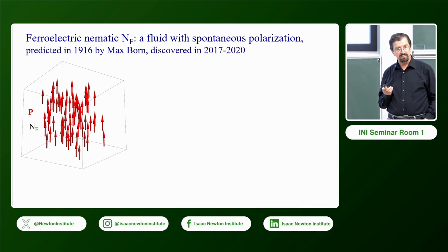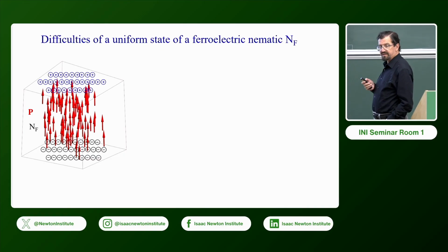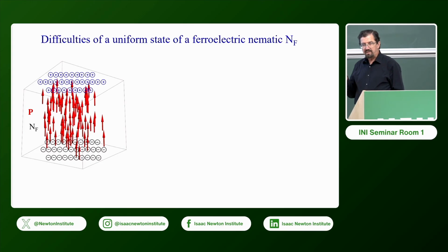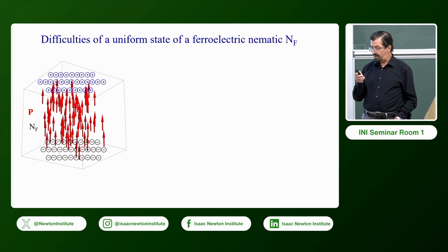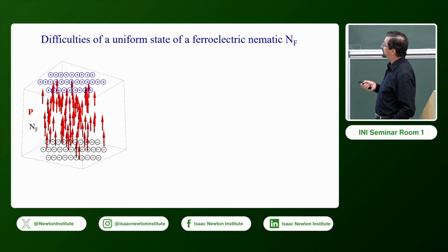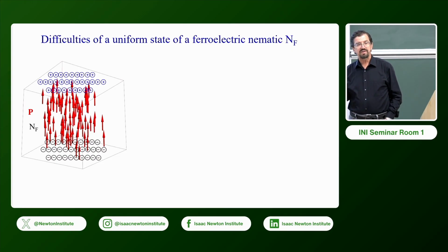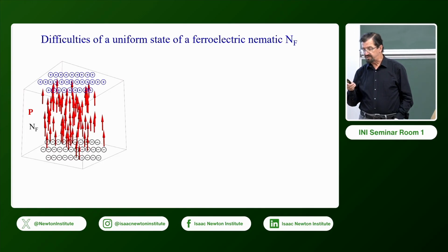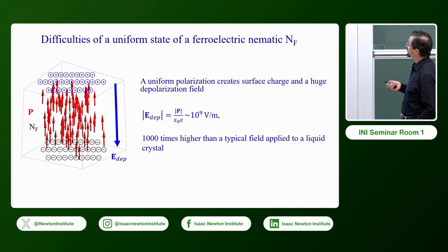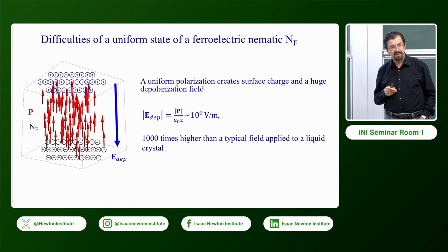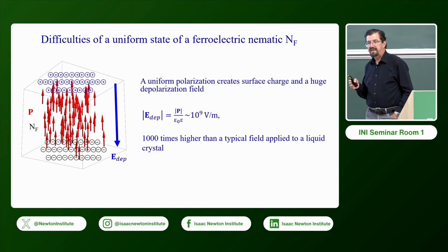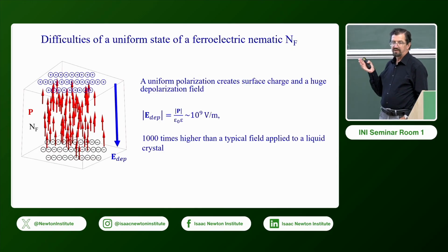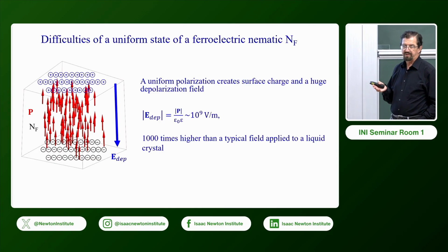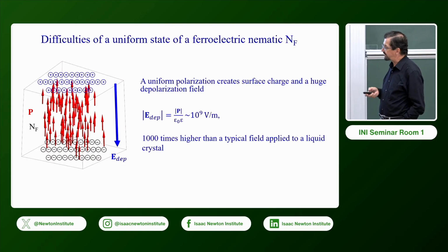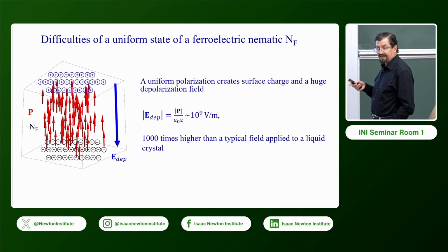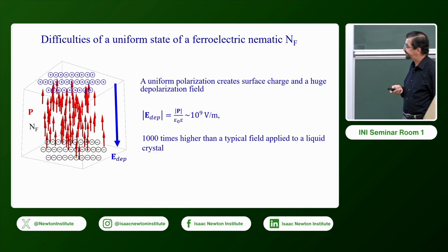But in fact, if you think a little bit more about this picture, you would realize that there is a problem. Any sample would have boundaries, and if the boundaries are perpendicular to the polarization vector, that deposits electric charges. And these electric charges would create the so-called depolarization field shown here. If you estimate this depolarization field, it's many, many orders of magnitude larger than the electric fields typically used in experimenting with nematic liquid crystals. It can even destroy the polarization order.